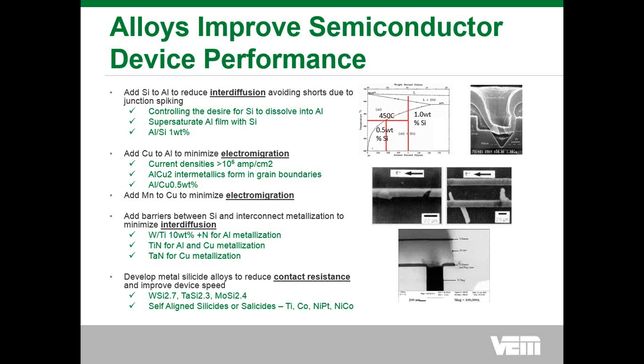So what the industry said is, well, if I can control the electromigration, what if I put a barrier between the aluminum and the aluminum copper, and then I can eliminate the problem of the silicon junction spiking and the precipitation of silicon in contact windows. So this is where we then moved into the barrier technology. And one of the more common alloys for barrier technology is the tungsten 10 weight percent titanium alloy.